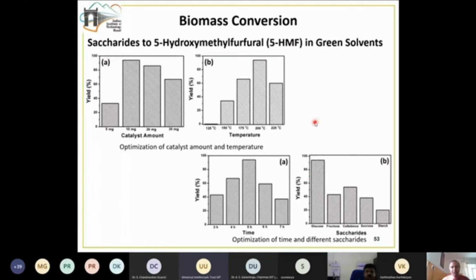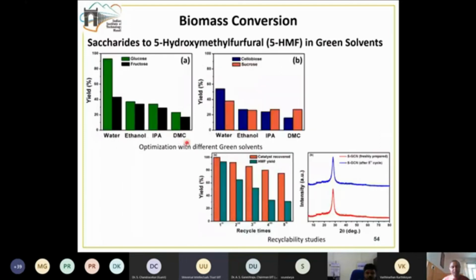We also studied different green solvents ranging from water, ethanol, IPA, and DMC, both for the monosaccharides and also for the polysaccharides. We also studied the recyclability and the stability of the catalyst after recyclability, because we wanted to ensure whether the sulfonation is still found in the catalyst or not, or whether there is any leaching of this functionalized sulfonyl group. And we were able to see that the catalyst is very stable.